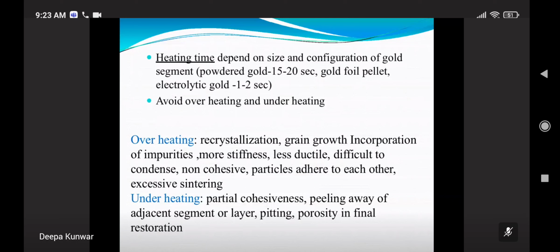Avoid overheating and underheating. When we do overheating, there will be recrystallization, grain growth, incorporation of impurities, more stiffness, less ductility. It will hamper the properties of the gold. Difficult to condense, non-cohesive particles adhere to each other, and excessive sintering. Underheating means partial cohesiveness, peeling away of adjacent segments or layers, and pitting and porosity will be there.